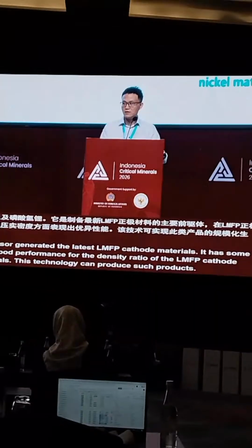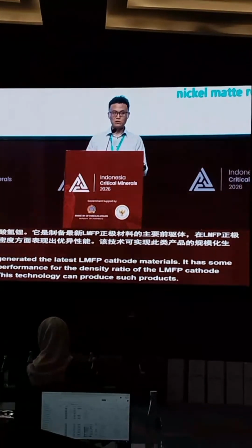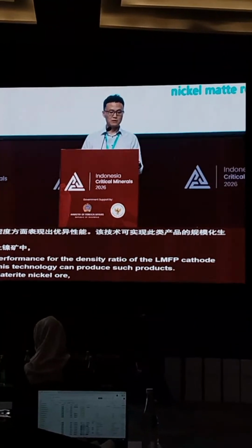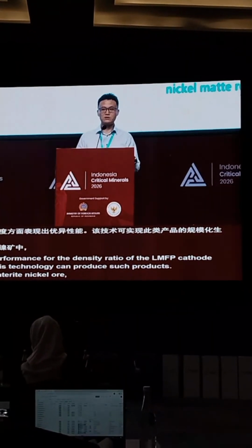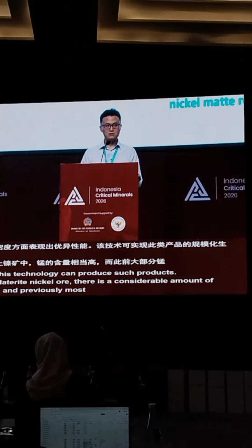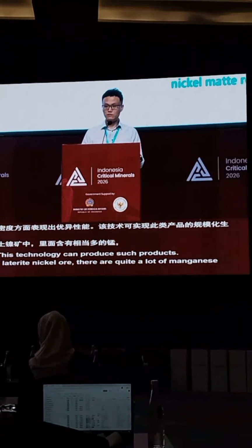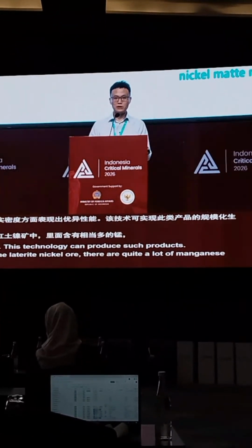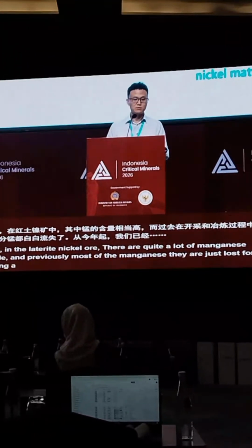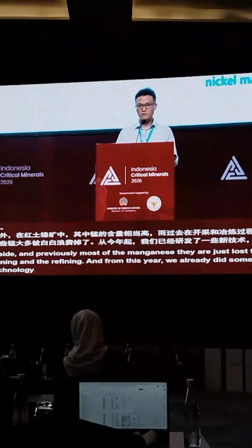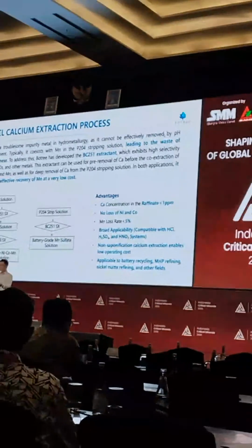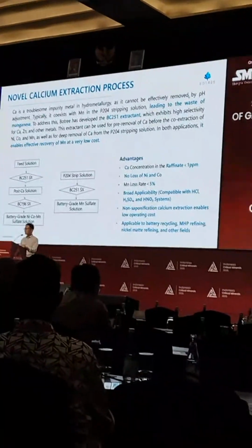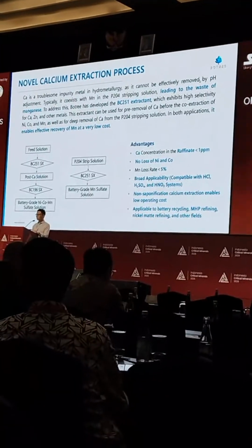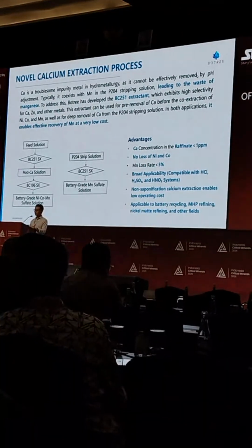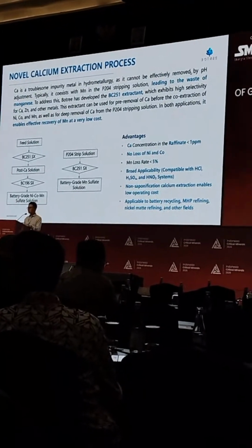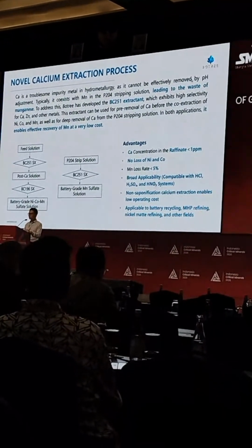Also, in the laterite nickel ore, there is a portion of manganese inside. Previously, most of the manganese was just lost during the mining and refining. From this year, we did some new technology, which will be used commercially from next month, to extract the manganese from the solution to produce manganese sulfate with battery grade that can also be used directly to produce the PCAM. And since we extract the manganese, it means that we can decrease the OPEX quite a lot.